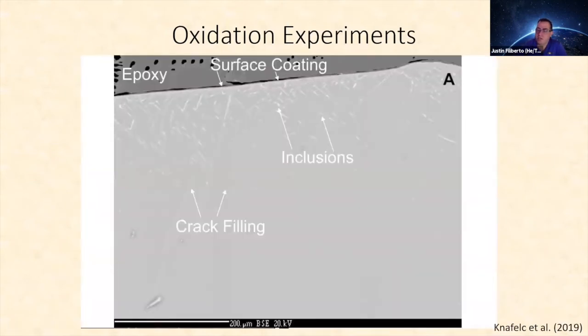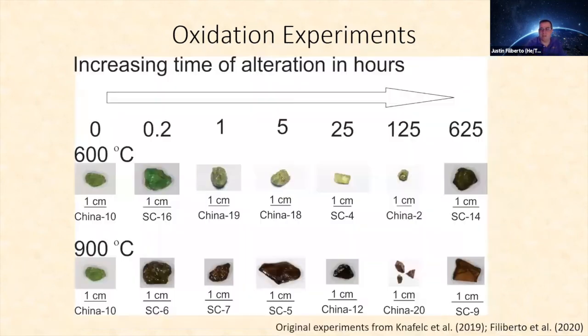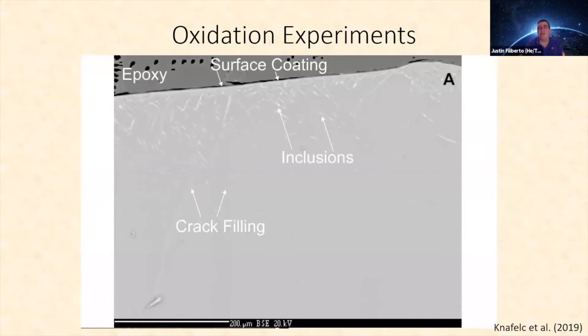We also cut through one of these and did SEM on this. This is the olivine in the interior. This is the oxide filling cracks. This is oxide inclusion within the olivine itself. And this is iron oxide coating the olivine. This is an experiment done, this one down here, so this is after a month at 900 degrees. And interestingly, when you look at a cross-section, you're still mostly seeing olivine in the interior, though the iron oxides are forming coatings and within the inclusion. However, if you broke the sample open, it's still mostly olivine.